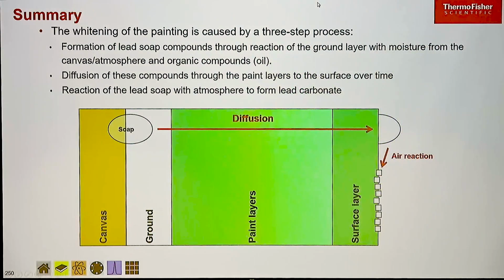We could skip through those ones. So what actually happened was that the guy was so keen on making his painting that he didn't dry the canvas properly. So there was still moisture within the canvas when you put on the ground layer here. And this is just that lead stack white. So basically lead carbonate dissolved in oil was painted over the surface of the canvas. Now that reacts with the moisture in the canvas and changes to form these soap compounds. And these soap compounds in history of art terms are very mobile, and in anyone else's terms are quite slow moving. But over 100 years, they went from the canvas all the way through these paint layers by diffusion to end up at the surface.